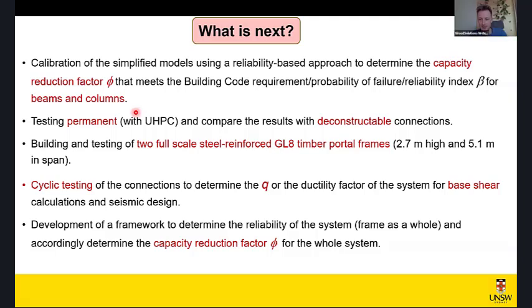Right. Fairly easy, straightforward. And after a day, we did some preliminary tests to make sure the quality of this ultra high performance concrete meets the expectations. We could get a strength of up to 55 MPa after 24 hours. Wow. Right? Tensile strength of 3-4 MPa, which is enough for adding the next level on top of that.